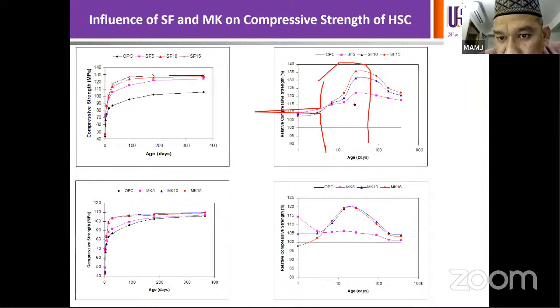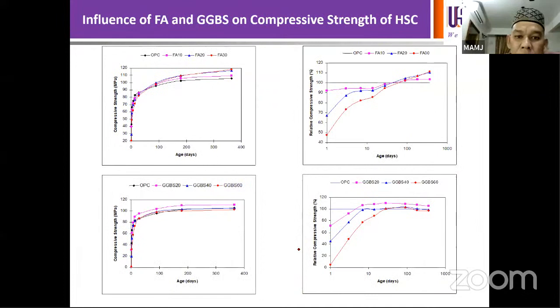So that could be associated with the pozzolanic reaction of the material. Okay. So in the case of silica fume, at 5 and 10, it is almost a similar trend. So there is an increase in relative strength, but at 15% there is a slight drop. So meaning that at 15%, the dilution effect may be more dominant at this particular stage at 15% silica fume content because of the reduction in cement content.